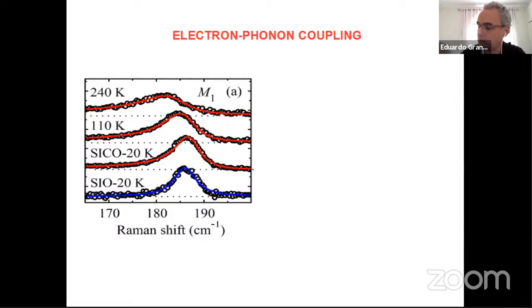except for a more detailed look at the electron-phonon coupling, looking again at the Raman scattering behavior of the system. Now I look at the Raman scattering as a function of temperature, and if I look at a specific phonon for the SiCO sample, the doped sample at low temperatures, you see that there is some asymmetric line shape. I will again not go through the full details of the reasoning, but that leads to the conclusion that we have electronic excitations which are of very low energy, and that's not expected for an insulating material. In an insulating material, we have a gap of at least, let's say, half an electron volt or tenths of electron volts.